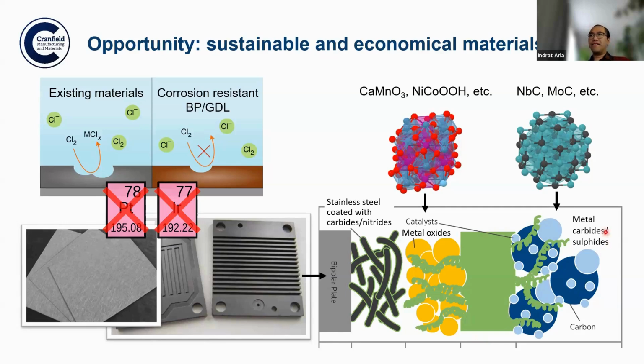Now, the good thing is that because these are oxides, the oxide is stable in oxidizing condition. So their consumption will be much less than if we just start with nickel metal, right? So then if we oxidize, we create an oxyhydroxide. The research is still ongoing, but we predict that the materials consumption will be at least 2 orders, if not 3 orders of magnitude lower than if we just start with a nickel metal.